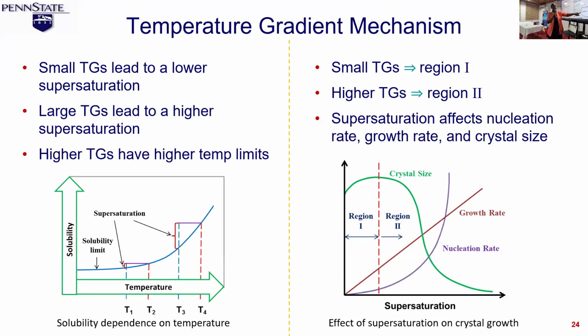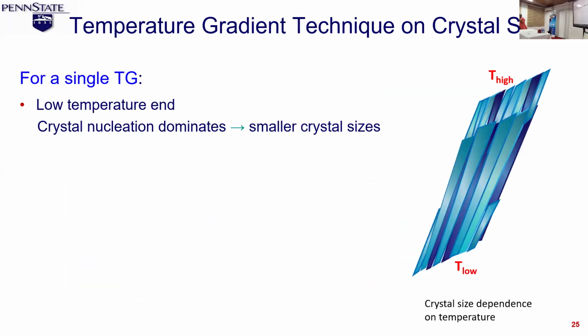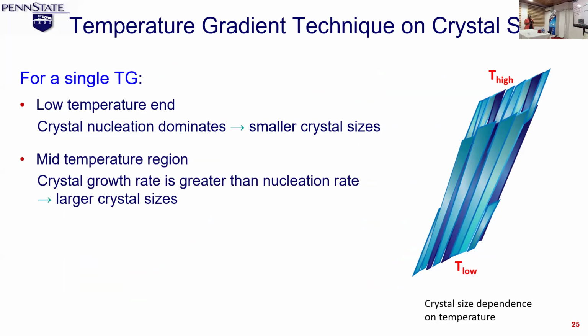And the reason is that there's a competition between nucleation and growth rate. You essentially want the growth rate to be higher than the nucleation rate, because if you just keep nucleating, you just have these solid particles in the solution and they are not going to crystallize, right? So we usually want to remain in this region for good crystal sizes. If we look at a single crystal that is created, on the low temperature end, nucleation dominates, so crystal sizes tend to be smaller. Somewhere in the mid-temperature region, the growth rate tends to be higher than the nucleation rate, so the crystal sizes start to get larger.